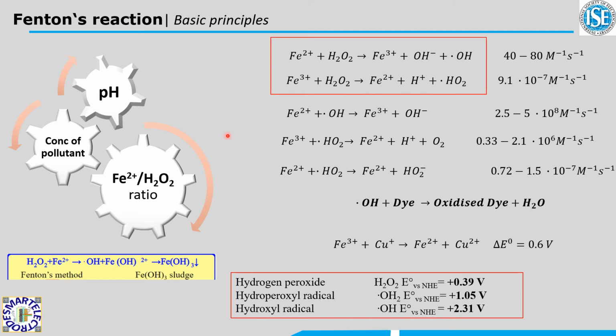Fenton's reactions, basic principles. pH, concentration of pollutant, and ratio between iron 2+ and hydrogen peroxide all have an effect on the overall rate of the breakdown reaction. Recommended pH range for Fenton reaction is around 2 to 3, where there is a constant supply of iron 2+ ions. At higher pH, 4 to 5, the formation of iron hydroxides occurs, which are insoluble in water, that form a sludge which later has to be removed. However, heterogeneous catalysts remedy this problem.